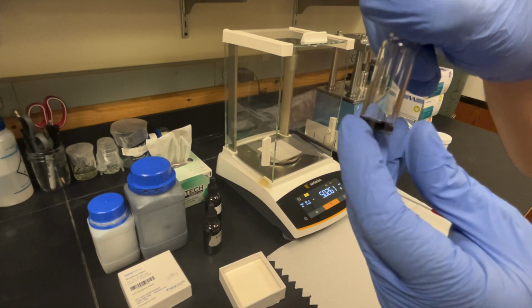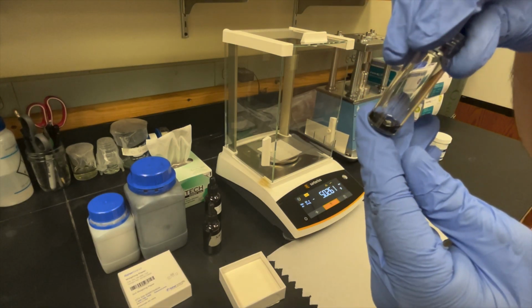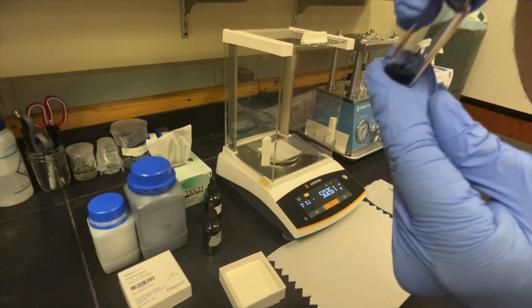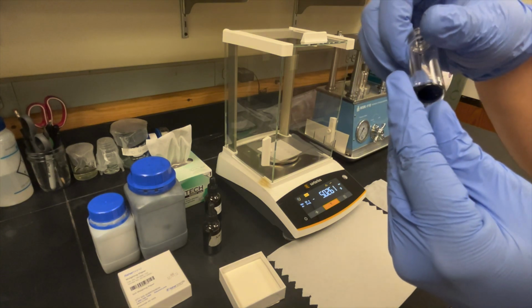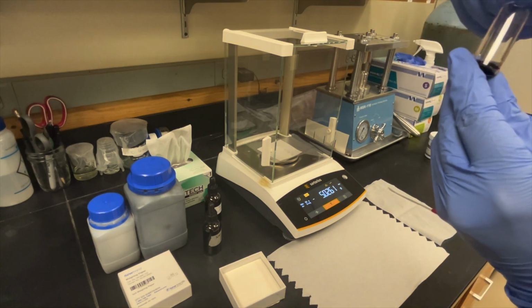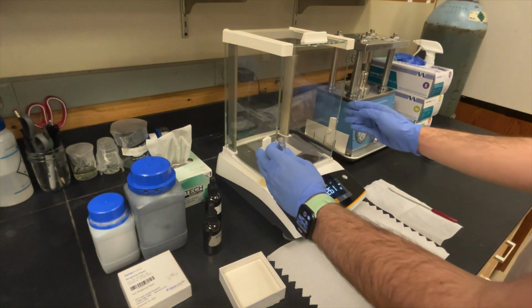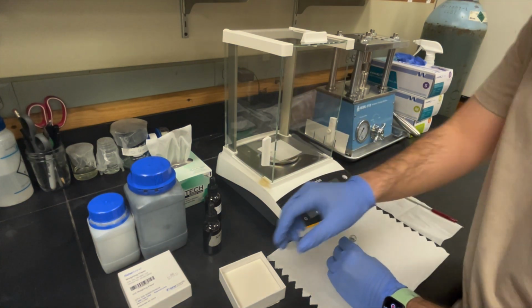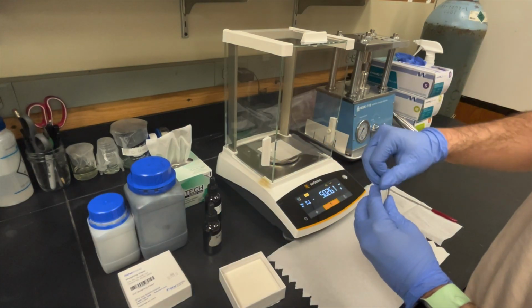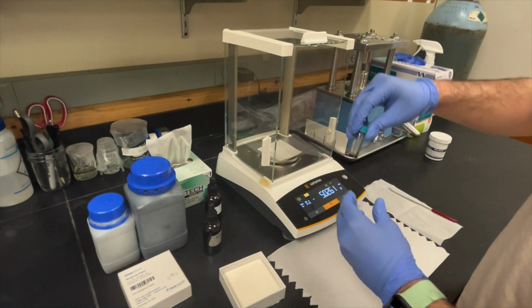After adding the solution, we may notice that it isn't quite homogeneous as we desire. We may then want to mix it over a vortex for the powder to soak in the solution, or we might add more solvent without PVDF so that we obtain the slightly runny consistency that is ideal for slurry depositions.